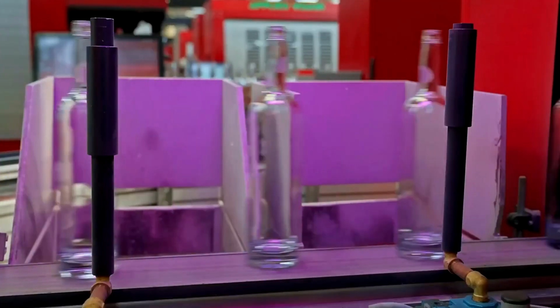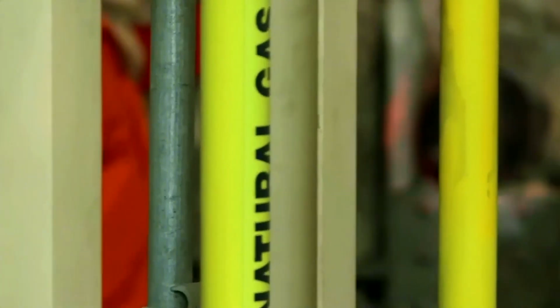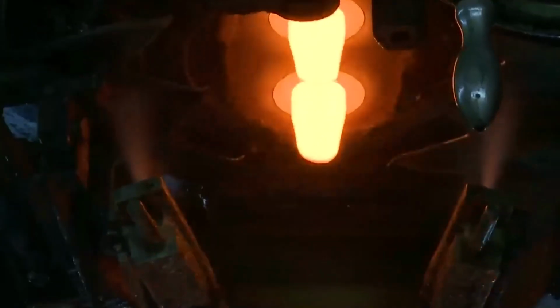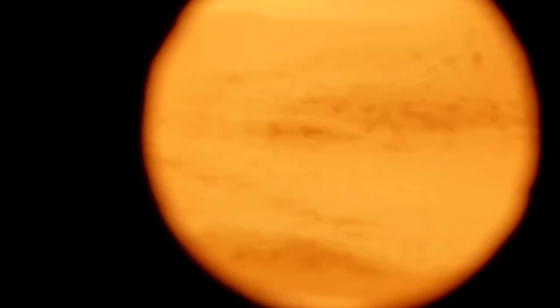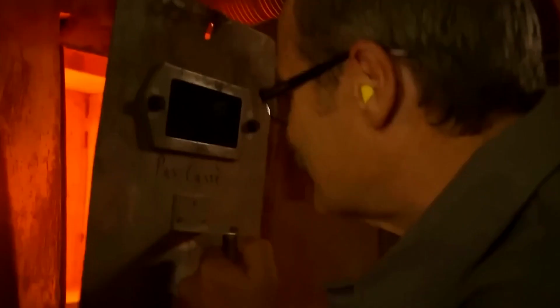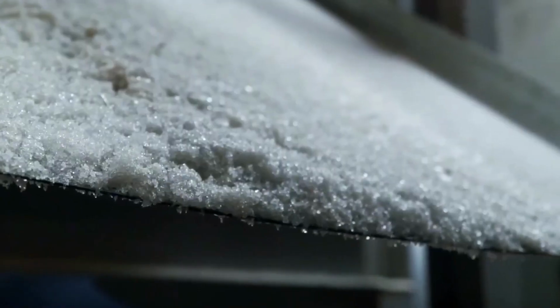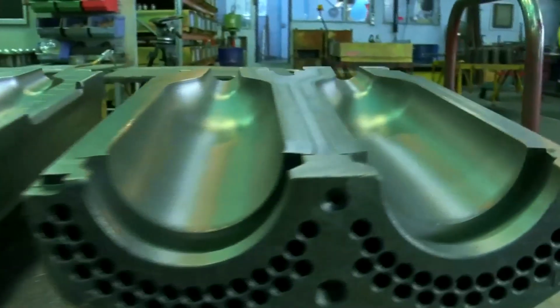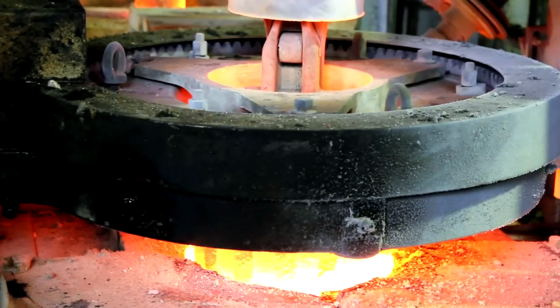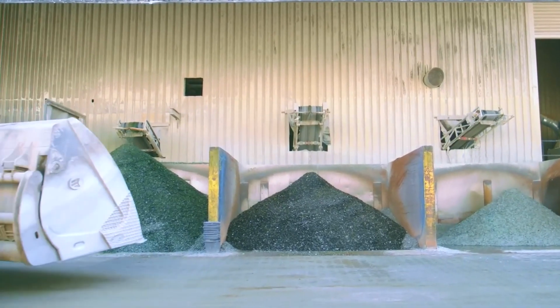Engineers employ advanced computer-aided design software to draft the mold with high precision, controlling every line, dimension, and thickness to meet rigorous technical standards. From this digital blueprint, molds are manufactured using cast iron or alloy steel, materials capable of withstanding temperatures of up to about 1,400 degrees. These forms are then prepared to receive the molten glass and shape it from the inside out.